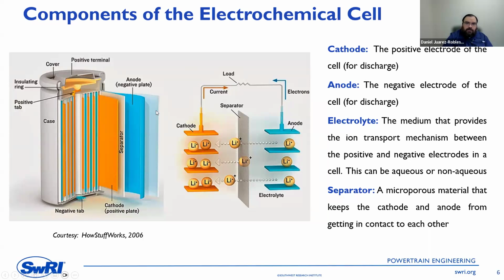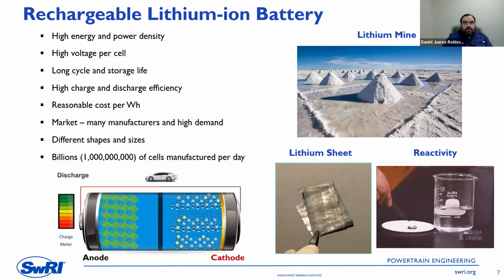electrolyte. Electrolyte in the lithium-ion battery is a combination of a solvent and a salt. Both of them are mixed, and it's not a single salt, there are multiple salts. But this ionic liquid will help you to move the ions from cathode to anode during charging and from anode to cathode during discharging. And since we don't have a direct contact between cathode and anode because all the energy will be released instantly, then we introduce a separator. The most common material is a microporous material that avoids having a direct contact.